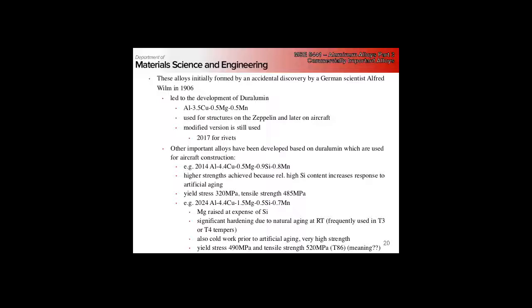So generally in the T8 you'll cold work before the T8, or when we get to other ones where you've got T8 and then two numbers after it, that's because when you quench it you get a lot of residual stress, and by doing plastic deformation after you relieve those stresses. Remember, residual stresses are elastic, caused by the thermal mismatch, and when you deform it plastically, you're applying a load over top of it, causing plastic deformation and removing some of those residual stresses.